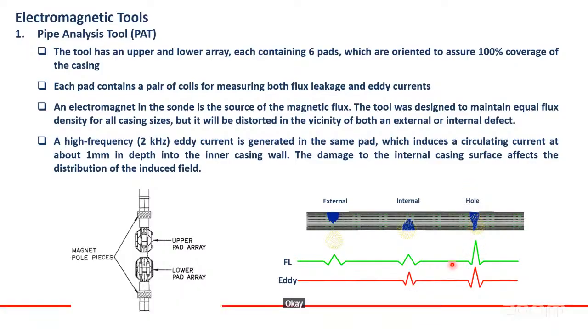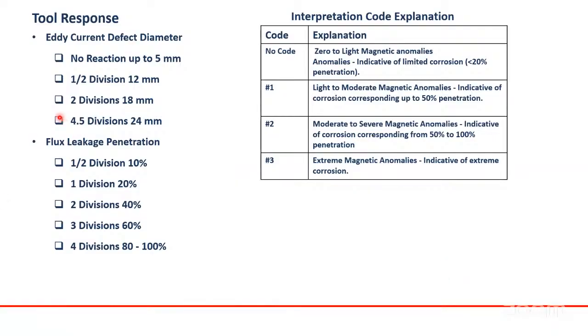In case of a hole, both of them give you a very high response. According to the eddy current defect diameter, it is measured and scaled. A half division is equal to 12 millimeter, two divisions is 18 millimeter, and 4.5 divisions is 24 millimeter. For flux leakage, a half division is 10%, one division is 20%, two divisions is 40%, three divisions is 60%, and four divisions is 80%.